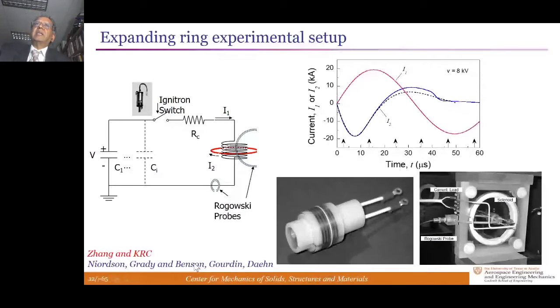The innovation that we brought to this problem was to take this specimen and fix it in a housing such that there was a clear path to view coaxially with the coil so that you'd be able to see the ring. Place that in a high-speed camera in a shadow mode so that you could see a shadow of the ring and take pictures at high framing rates. So these are pictures that are taken once every 10 microseconds.